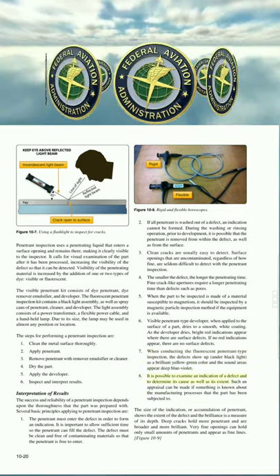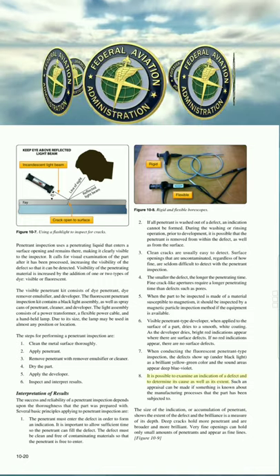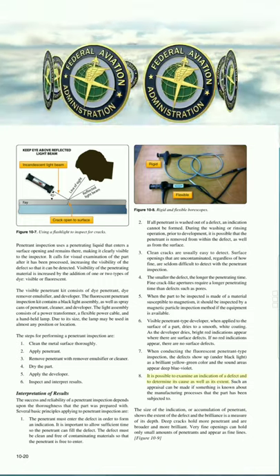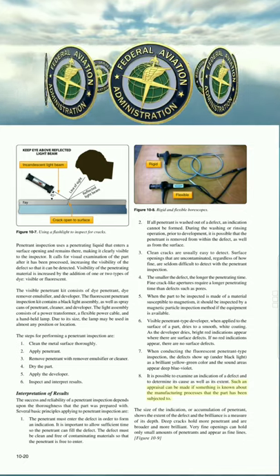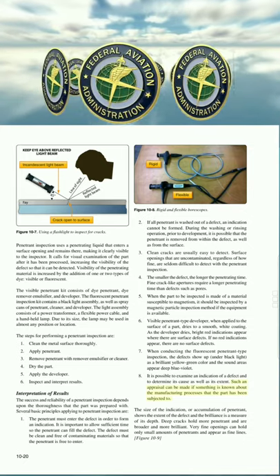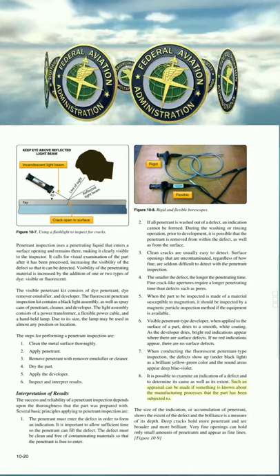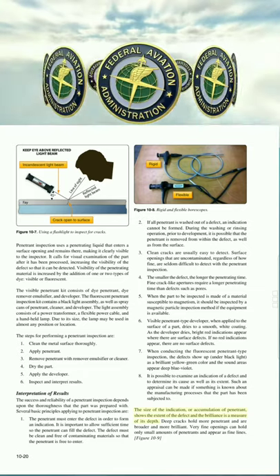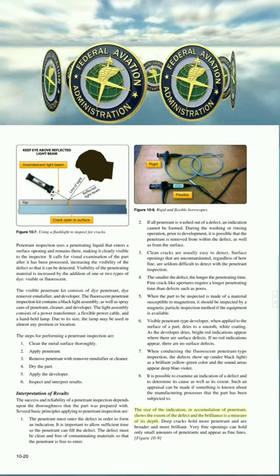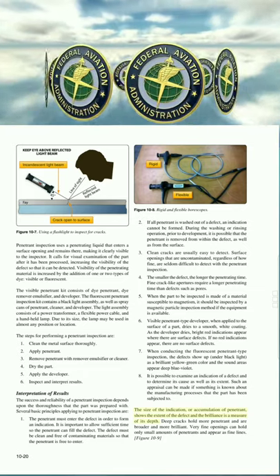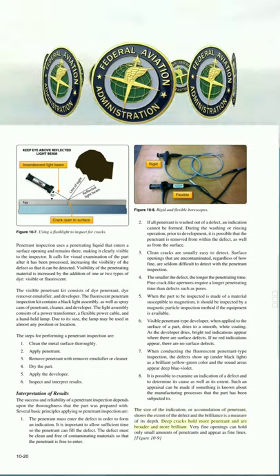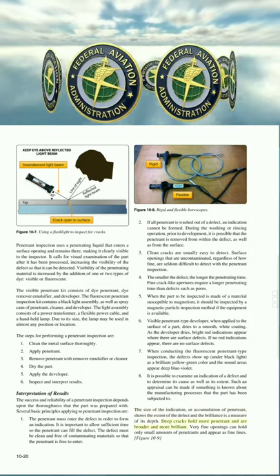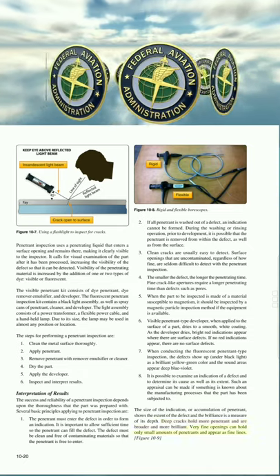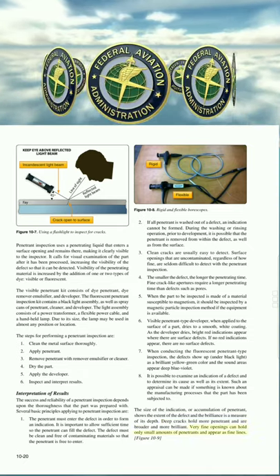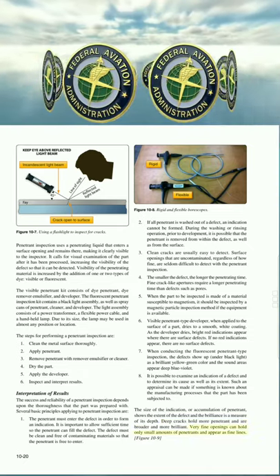8. It is possible to examine an indication of a defect and to determine its cause as well as its extent. Such an appraisal can be made if something is known about the manufacturing processes that the part has been subjected to. The size of the indication, or accumulation of penetrant, shows the extent of the defect, and the brilliance is a measure of its depth. Deep cracks hold more penetrant, and are broader and more brilliant. Very fine openings can hold only small amounts of penetrants and appear as fine lines.